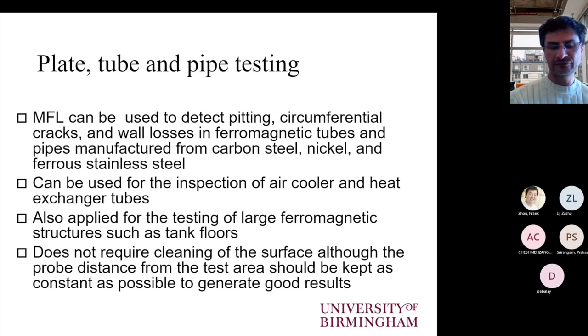In the case of MFL, the advantage is that despite the fact that we don't have accurate quantification, we have the capability of getting a good qualitative assessment, and we can get some semi-quantitative idea of the defect severity. The other advantage is that it does not require excessive cleaning, which is the case for eddy-current testing due to the higher sensitivity that this method has to liftoff. So with MFL, we can do the inspection with, let's say, an inferior level of cleaning, but we do have to take into account that any changes in the distance between the probe and the test piece can result in signals that are not true. So we have to ignore them.